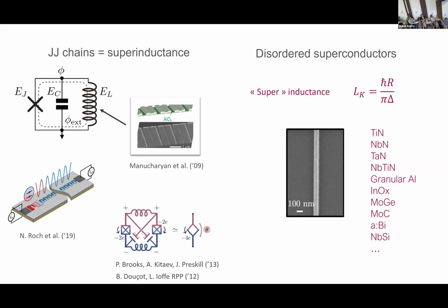So in the same device, you have a square which is 1 micron, so ridiculously small that you cannot couple to everything, but it's a junction where the self-capacitance is the capacitance of the transmon, and all the electric field is only through a crystalline insulating barrier. So it's not a disordered material; it's the 2D materials aspect for application. So far, nobody has made this kind of ultra-small qubit, which, by the way, cannot be scalable because they are too small to couple. But you can imagine adding more layers of BN and making a bigger surface. Yeah, from the semiconductor industry, there is a push to have 2D materials grown properly, or at least selective-area grown. So, I mean, there is maybe a future where you can make this easier than just stamping flakes.